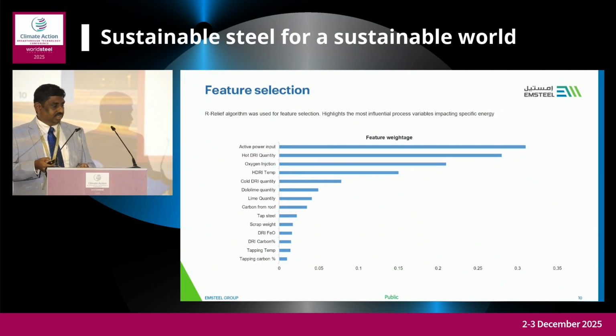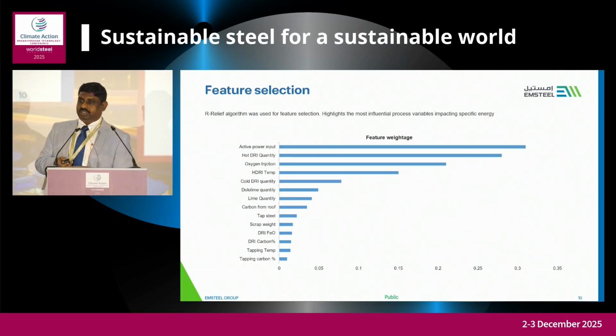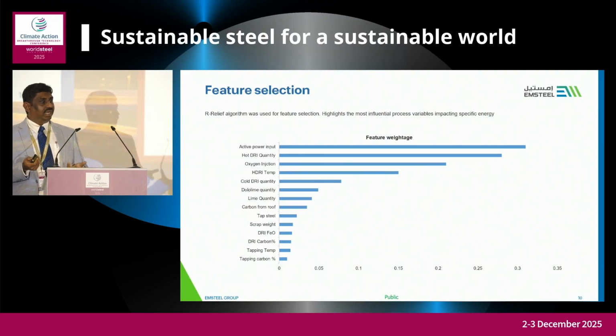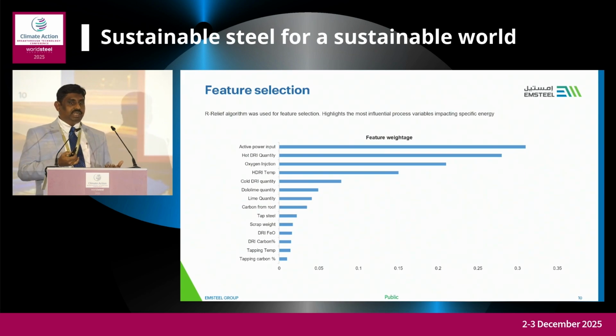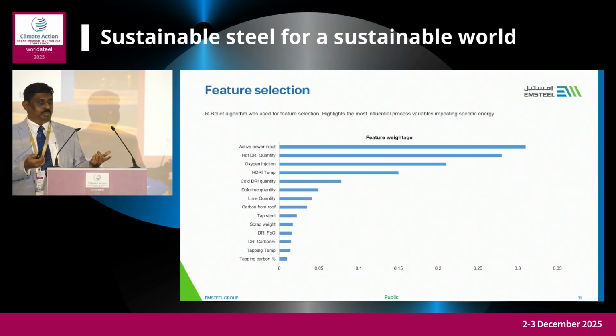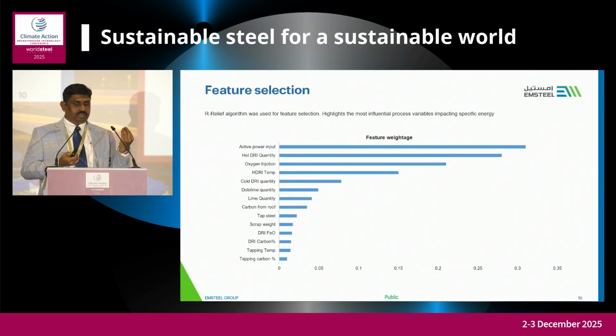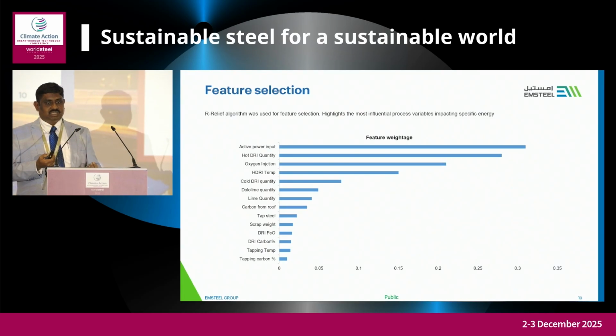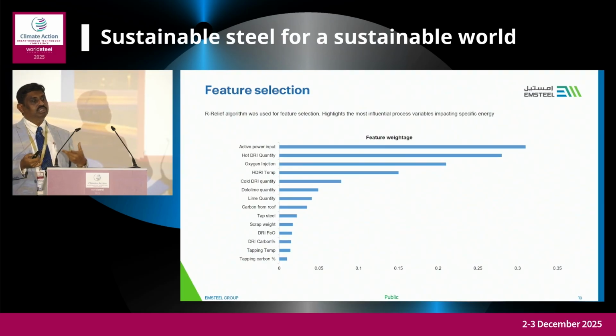That we have done. Then, we have run different feature selections, which are machine learning tools like mRMR, R-square, ReliefF. Based on these algorithms, we compare the best performance of the features impacting the process. We also validate these features against the metallurgical process. In the electric furnace, active power is the most important factor to control the energy. Next are the hot DRI temperature, hot DRI quantity, and our oxygen injection. These are the most important parameters controlling the energy.